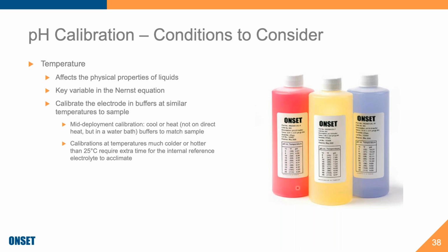So one thing with pH 4 is it's a very stable pH buffer. It maintains value really well. It maintains value at different temperatures really well. As you can see, it's 4.01 and then 4.00 for a lot, and then 4.01. It's only at the high temperatures where you start seeing it changing. Whereas with pH 7, when you see 0 to 45 degrees Celsius, the pH will go from 7.12 through the 7 at 25 degrees and then down to 6.97.